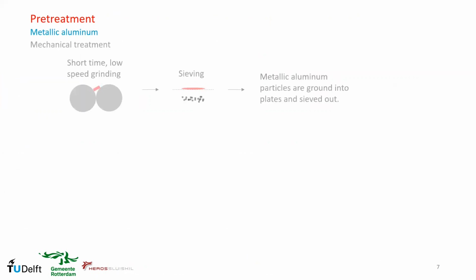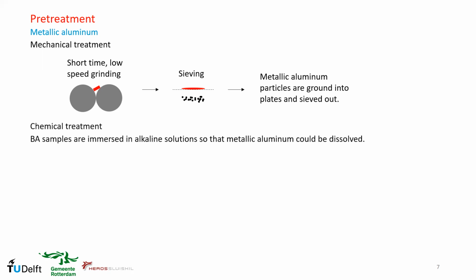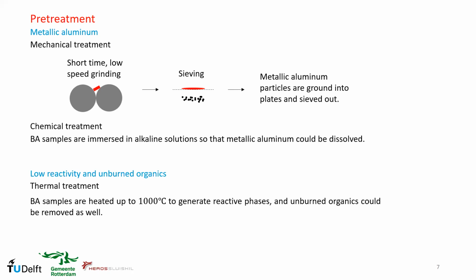Regarding the metallic aluminum content, the first method is mechanical treatment, which is a low-speed grinding process for a short while, so that the metallic aluminum could be ground into plates and then sieved out. There is also chemical treatment, where the bottom ash samples are immersed in an alkaline solution so that the metallic aluminum could be directly dissolved. And regarding the low reactivity and unburnt organics, thermal treatment is possible by heating up to 1000 degrees Celsius to generate some reactive phases, and the unburnt organics could be removed as well.